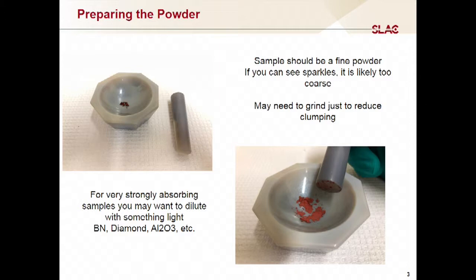Alumina is pretty good. This is also nice because it can give you kind of an internal standard if it's a very well-known material. If you know, for example, exactly what the lattice parameter of this is, you can be very sure that you can know the lattice parameter of your sample because you can calibrate it to what's already in the sample that you're measuring at the same time.